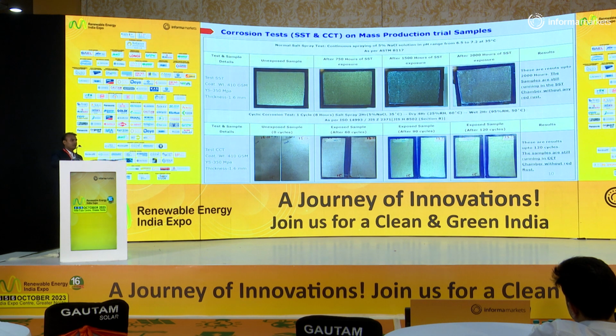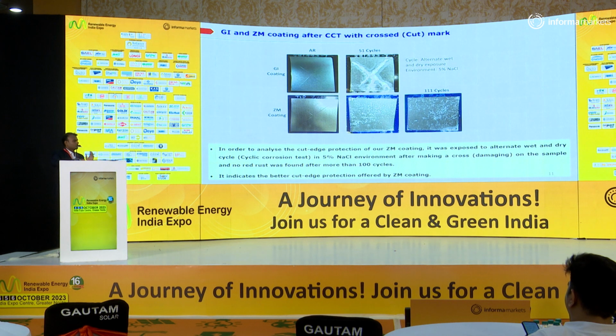In the actual environment where any solar structure is there, the environment will not be so harsh. So the material is performing well even in such harsh environments. It will be very well suited for the actual conditions in which your solar structure will stand. To test the cut edge protection, which is one of the characteristic features of this coating, we cross-cut one GI sample and one ZM sample, and it is observed that no red rust appeared, and the cut got filled after about 100 cycles in the CCT.